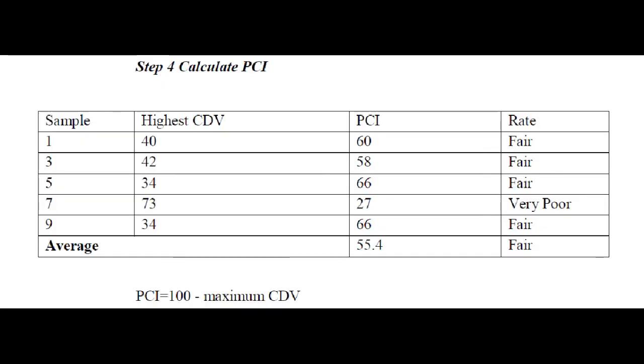So after every trial, we have selected the highest CDV from every sample. PCI is obtained by deducting the CDV from 100. The PCI are 60, 58, 66, 27, and 66 respectively for all the samples. We calculate the average and get 55.4 to be the overall PCI.